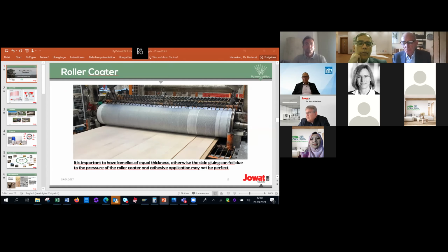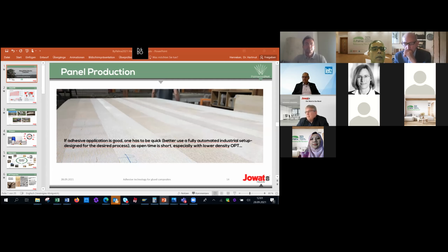You can also see here that this lamella has less glue on it, and here this is a little higher. There was a lot of pressure on it, and the side gluing was breaking up. So it's very important to have evenly distributed lamellas of equal thickness. Otherwise, these processes could fail. But as you see, it was possible.